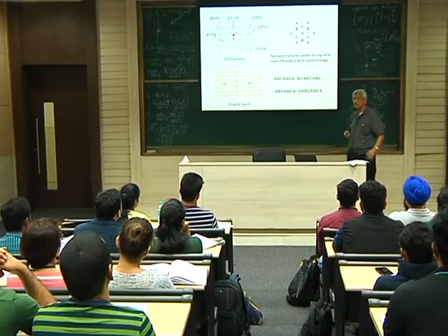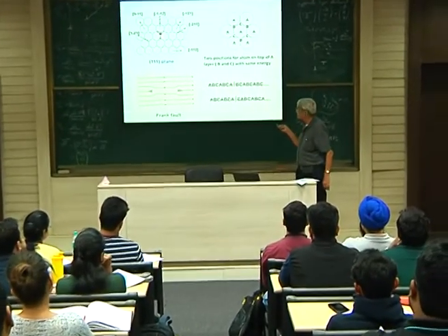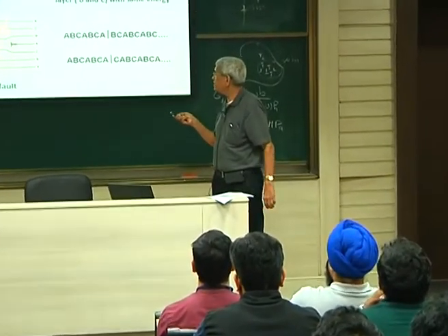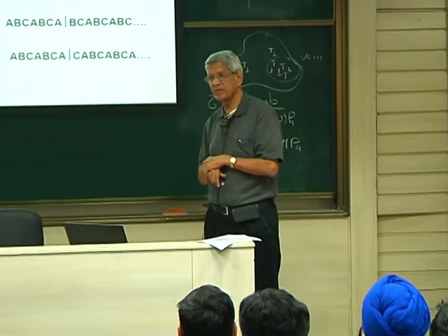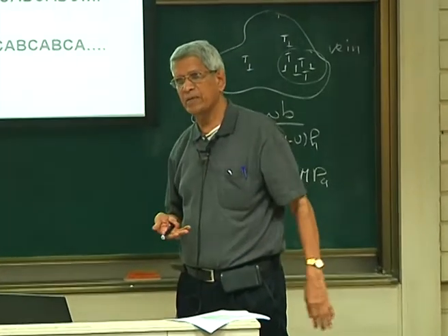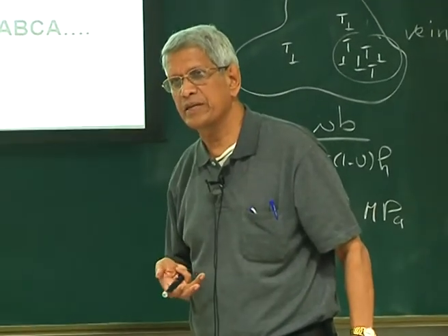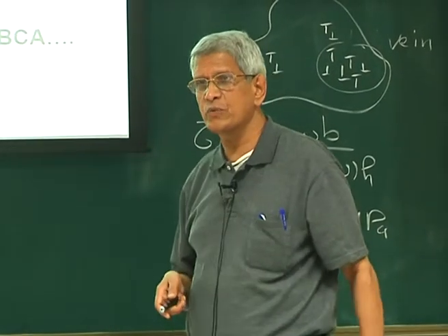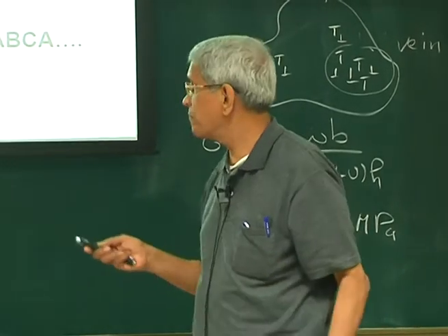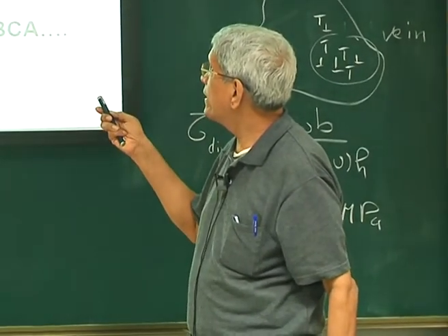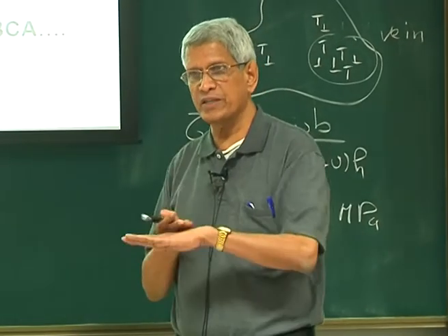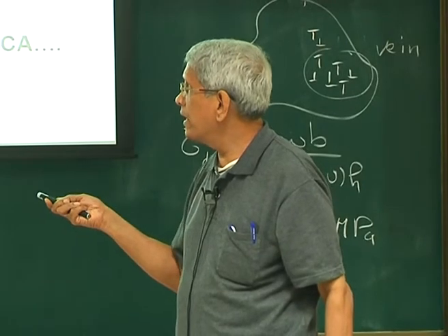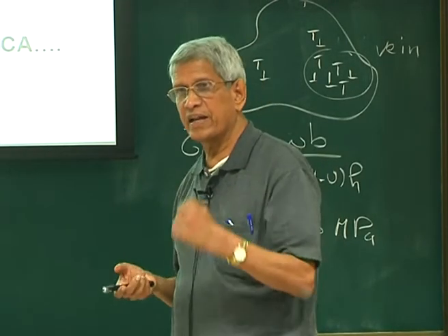Okay. Now, because of this, a stacking fault is created in the sample. Similarly, in the ABC stacking, as Marc Fivel explained yesterday, by removal of a layer, a stacking fault could also be created. If you look at the stacking fault sequence, it remains the same in either case, whether by displacement of an atom from one position to another in the stacking sequence, or by removing or adding a layer.